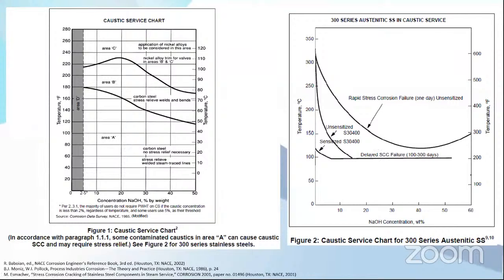And okay, this is the curve, the chart where materials can operate. For example, if you see on the left side, area A is for carbon steel without post-weld heat treatment. So in the caustic, for example, in 30% caustic natrium hydroxide, if you are using carbon steel without post-welding treatment, you can operate to 60 Celsius. If you want to operate in 70 Celsius, then you have to post-welding treat the carbon steel. But if you want to operate even more, for example, in 100 Celsius, then you need to change the material to nickel alloys, or it will still crack even if you already post-welded it.